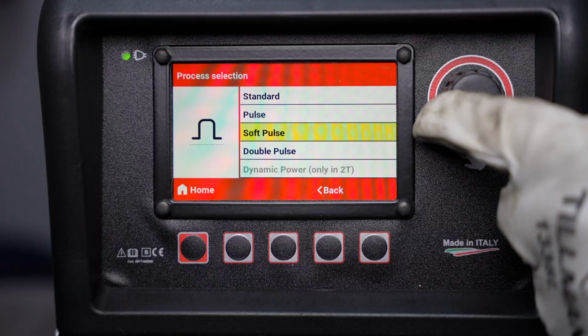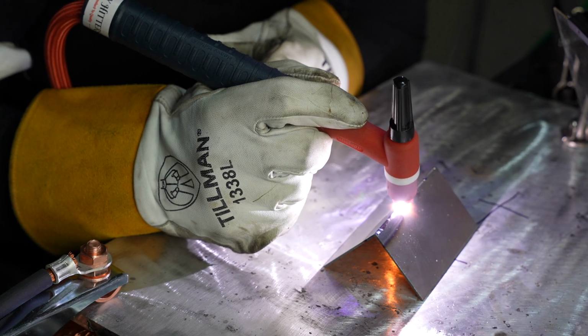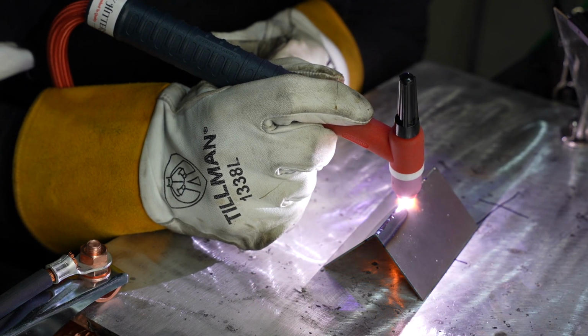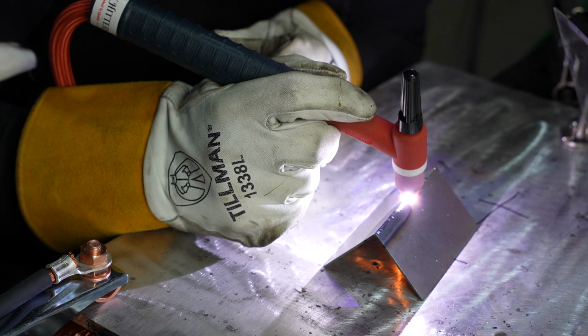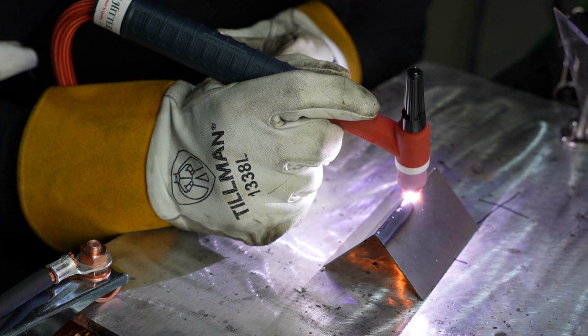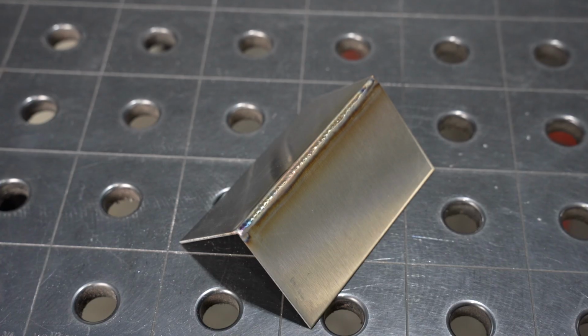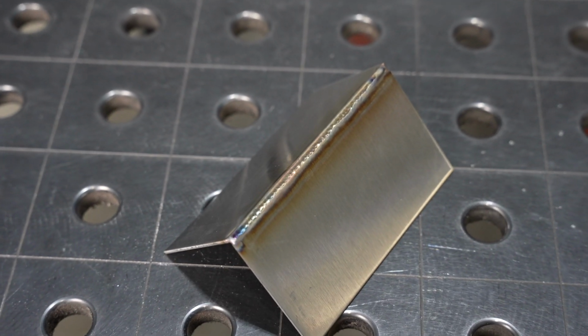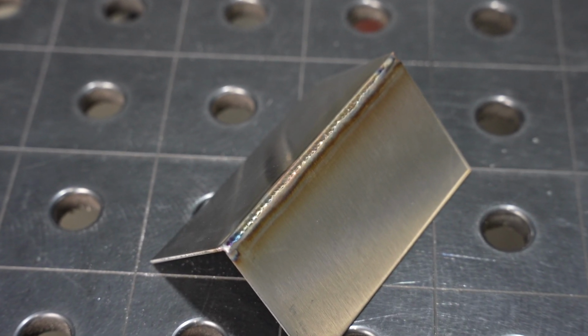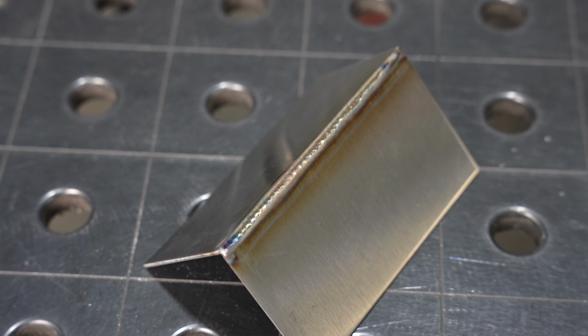You also have a soft pulse feature, which reduces the harshness of the noise from the pulse welding and gives a slightly softer arc when you're welding. There's also double pulse, which combines a high frequency pulse to give you a nice focused arc and reduced heat input with a low frequency pulse, which can help pace progression and give a rippled appearance. You can see the outcome of double pulse here on this stainless steel weld.